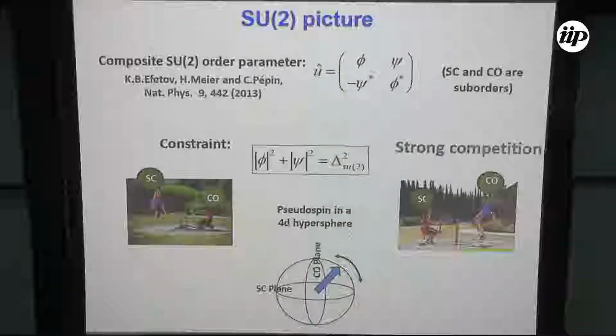What happens, because of this nature of the matrix, phi squared plus psi squared will be a constant on the right-hand side. If this constant is fixed, it's easily seen that there is a very strong competition between the two orders. If superconductivity is high, then the charge order has to be low because the right-hand side is constant. If the superconductivity is low, then the charge order will be high because the right-hand side is the same. So there is a very strong competition between the two.